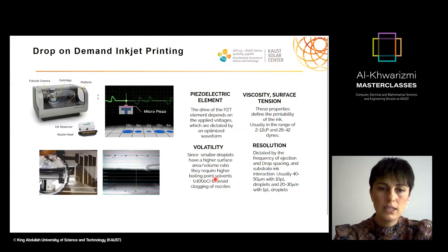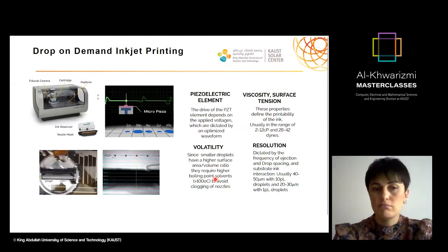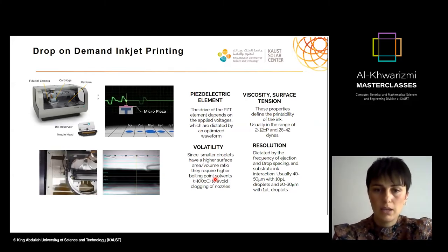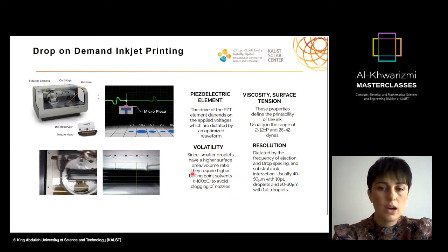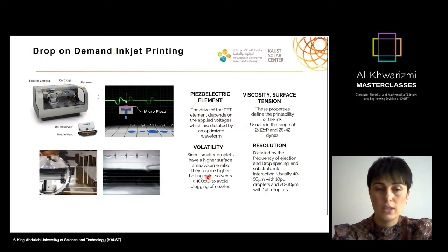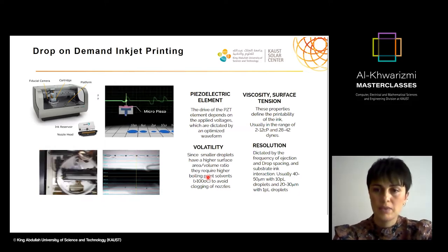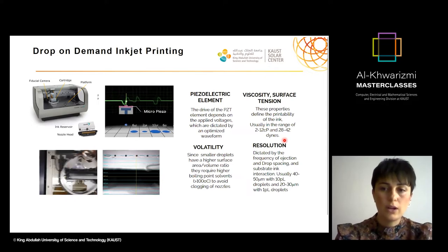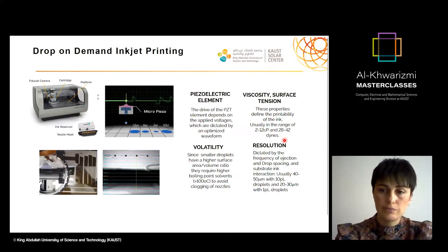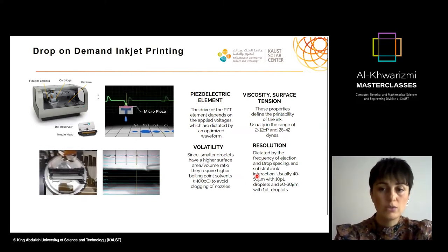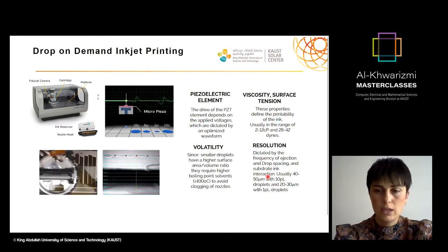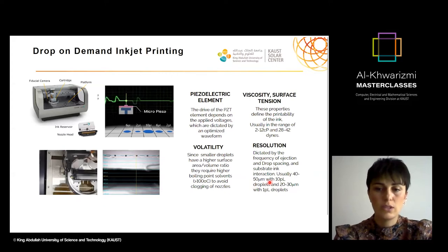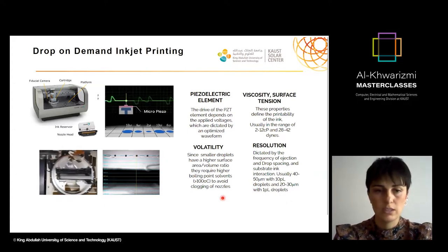And in terms of volatility, that's also very much affecting your printing, because if you have smaller droplets and so on and so forth, you need to think of what kind of solvents you need to use not to have any clogging in your printing. And in order to have fine resolution, obviously in the end, you need to optimize your drop spacing and substrate-ink interaction, which is very, very critical, and I will show you why it's very important. So then with different droplet amounts, you can achieve different resolutions, as you see here.